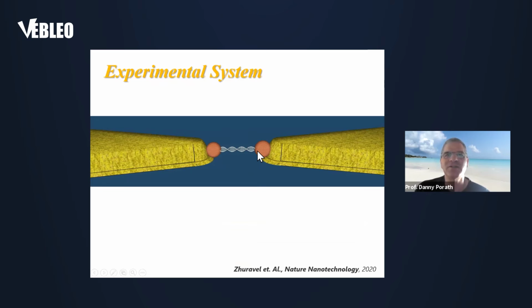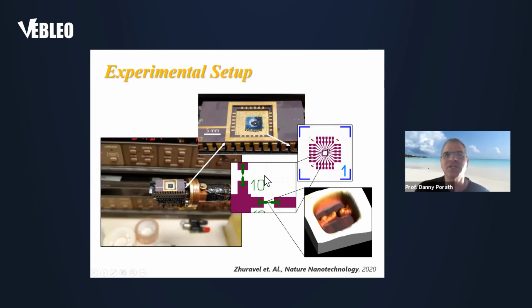This is a single double-stranded DNA molecule connected to two nanoparticles by thiols or by other means. And the dimer is connected to the tail electrodes and raised above the surface such that we can perform good measurements. These nanoparticles can report and tell us that the dimer is indeed trapped between the electrodes. So that's very important. And also, they provide good contact to the electrodes.